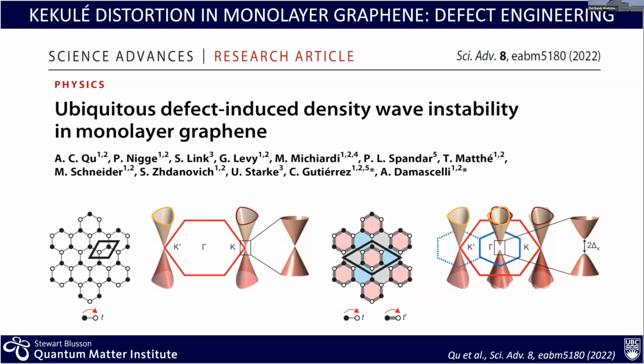Graphene has all kinds of possible orders that have been brought up. An interesting one is the Kekulé bond order, where you have modulation of the hopping parameters along the bonds. So you have strong bonds and weaker bonds. This leads to a larger unit cell, √3 by √3, rotated by 30 degrees. Effectively, in the electronic structure, the K and K prime Dirac cones are all folded down to the gamma point, now become equivalent, and a gap opens up.